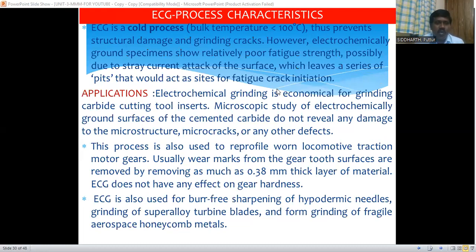Coming to the last point of the characteristics, electrochemical grinding is a cold process, meaning the temperature produced during this machining process is less than 100 degrees centigrade. Because of the lower temperature, it prevents structural damage and grinding cracks. However, electrochemically ground specimens show relatively poor fatigue strength, possibly due to stray current attack of the workpiece surface, which leaves a series of pits that act as sites for fatigue crack initiation. Finally, the components we produce by this electrochemical grinding process have less fatigue strength.